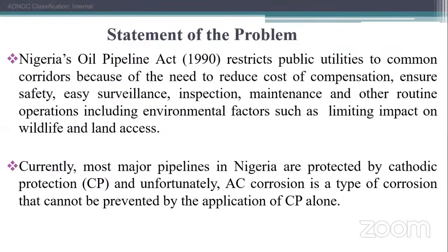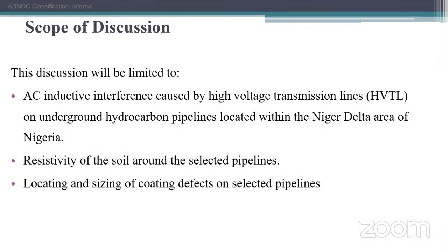For the other forms, the lesser the coating defect, the lesser the chances of corrosion happening. Like if my coating is good and I have an effective cathodic protection, those forms of corrosion may likely never happen. But alternating current corrosion is unique because it's the reverse of other forms of corrosion. The smaller the coating defect, the more the tendency of alternating current corrosion happening. It will prefer a bigger opening of the coating on the pipeline than even smaller, meaning that the smaller the coating defect, the more the tendency of alternating current corrosion to happen.